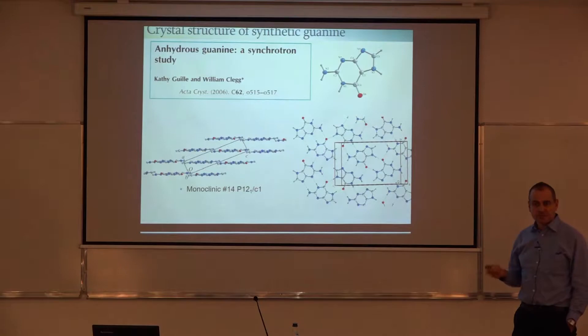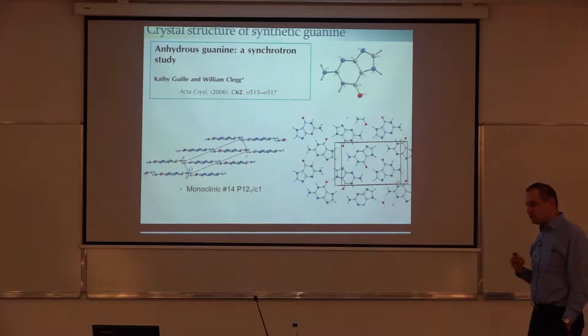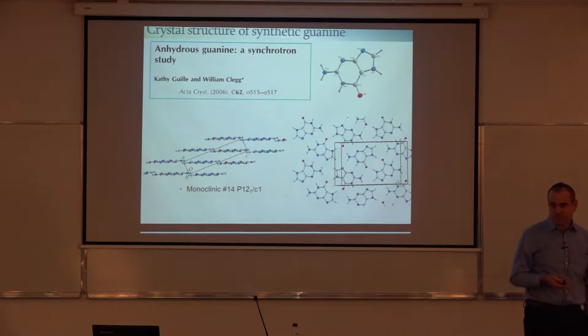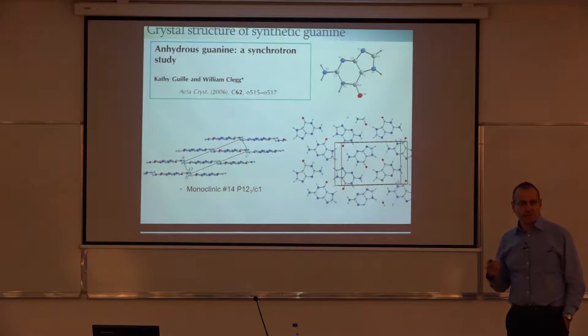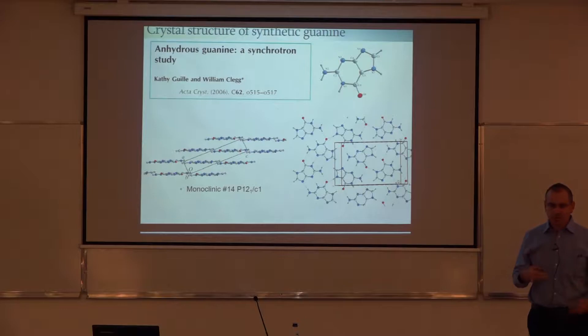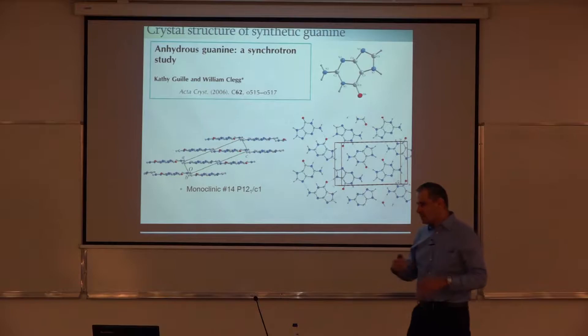The scientific question is: what's the crystal structure? If it's a crystal, what is the crystal structure? Surprisingly, the first attempt to really address that is rather recent — from 2006. The biological crystals are very small, so it's very hard to infer the structure directly. A group in Newcastle in England said: if we can't work with the biological samples, let's synthesize it in the lab. They created those crystals artificially and solved the structure using x-ray diffraction-based methods. They came up with a very interesting 2D structure: individual layers that are stacked on top of each other, similar to graphite or boron nitride.